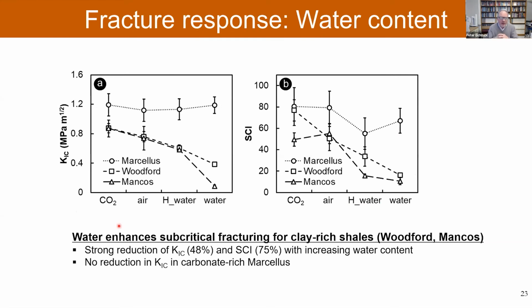So I'm showing you now, I'm not going to show you a lot of the data here, just to give you a flavor of it. The first one here is the 3 shales as they behave with varying water content. So this is CO2, which is very dry, air, which has 50% humidity or even more some days, and then submerged in water with the coating or without the coating. On the vertical axis, you have the fracture toughness, which describes the sudden fracture propagation behavior. And on the right side, it's the subcritical index, which describes the slow chemically assisted fracture growth.